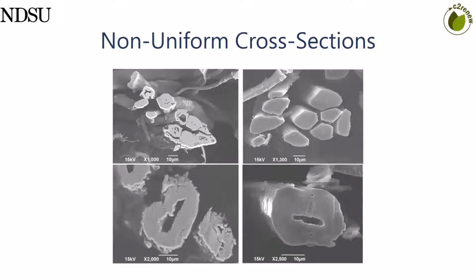I talked a little bit already about the time in which you should harvest the fiber, the optimal time. Depending upon the variety, the growing conditions and the time of year, sometimes you can have natural fibers that have a very closed, uniform cross-section, whereas later on in the growth process, they develop what's known as a centered lumen. That lumen can be a source of weakness in the fiber, especially if it gets too big, and you cannot penetrate the lumen with resin unless you use a high type of vacuum in order to fully infiltrate the center lumen and fully wet it out.